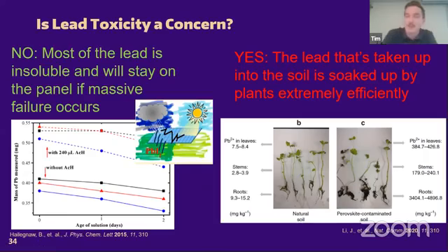Perhaps getting on my soapbox for a little bit, there are ways to make perovskite solar cells that don't leach lead into groundwater. You can easily control what happens if there is a catastrophic failure where water flows. We can create lead filters at the bottom of every solar cell. We could even do something that has been done in a recent report as well, where we mix a little bit of lead fixation molecules into either our encapsulant layer or into the solar cell itself.